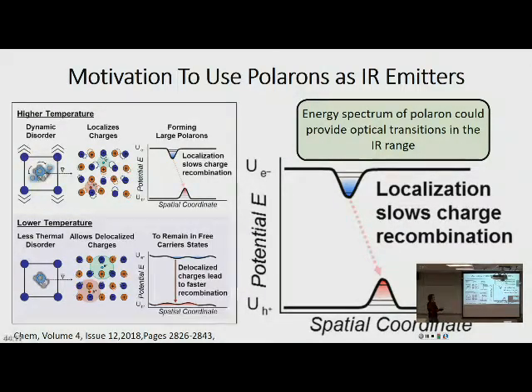Yeah, I guess as a first approximation to the energy spectrum within the well, you could just do a mean field, the same idea behind Coulomb binding or the exciton spectrum. The potential is created by distortions of the lattice, and the charge carrier can be excited through these quantized levels. The distortion of the lattice is stronger near the center of the polaron and decreases to zero as one goes apart. This approximately goes as 1 over r, and it creates an effective potential similar to hydrogen.